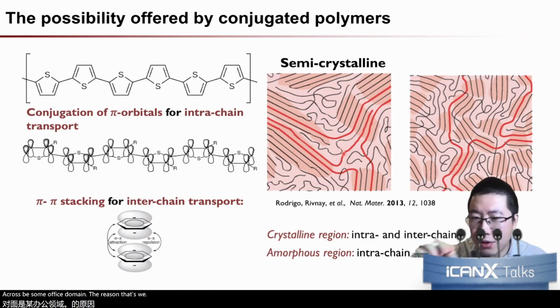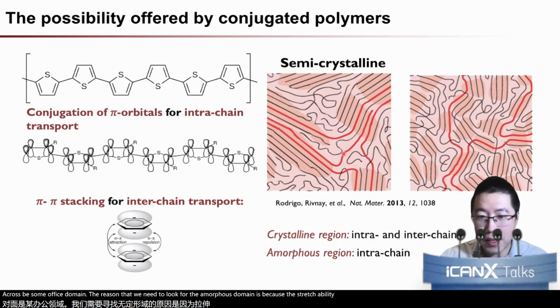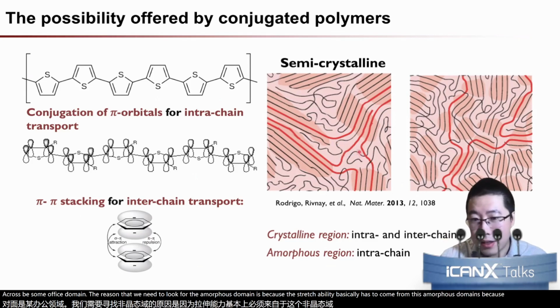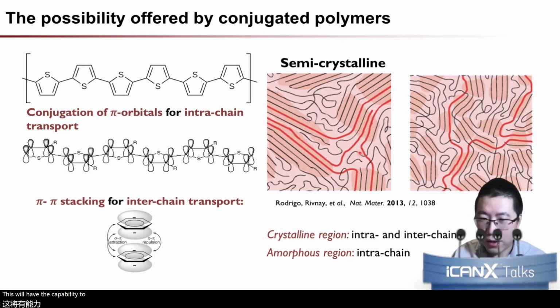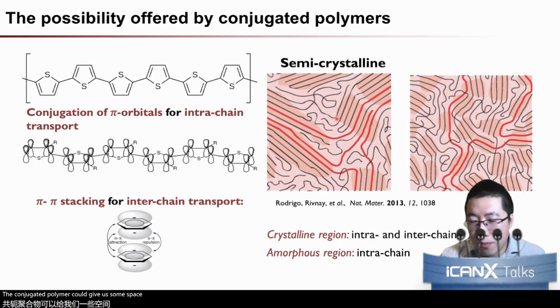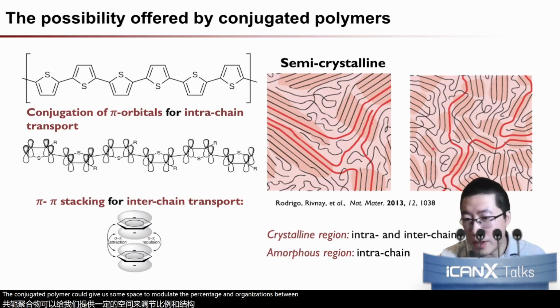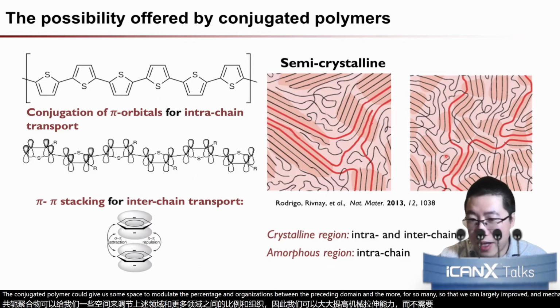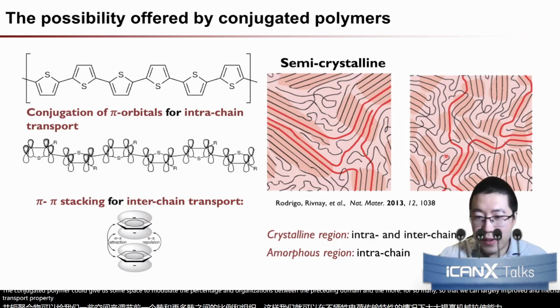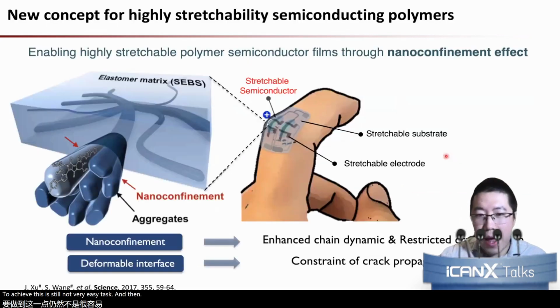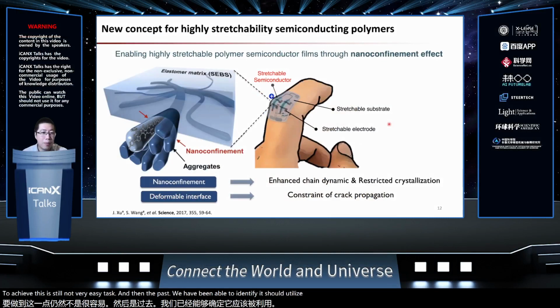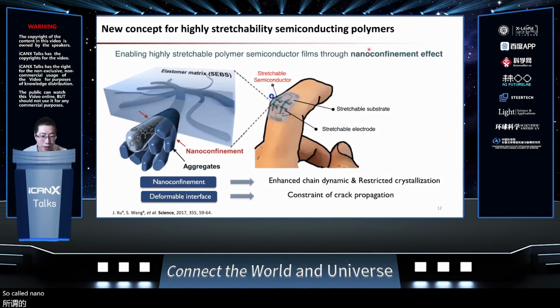The reason that we need to look for the amorphous domain is because the stretchability basically has to come from this amorphous domain, because it has the capability to let the chains reorient to dissipate the strain. Therefore, the conjugated polymer could give us some space to modulate the percentage and organization between the crystalline domain and the amorphous domain, so that we can largely improve the mechanical stretchability without much sacrificing the charge transport property. To achieve this is still not a very easy task. The path we have been able to identify is to utilize a polymer physics phenomenon, so-called nano-confinement, which is basically a nanoscience effect that's placed on polymers.